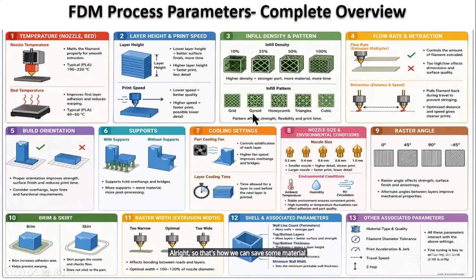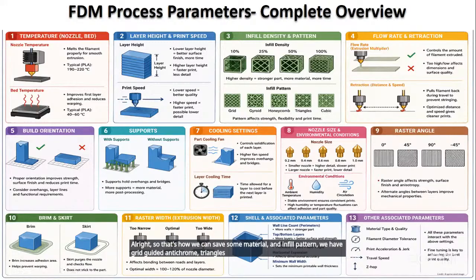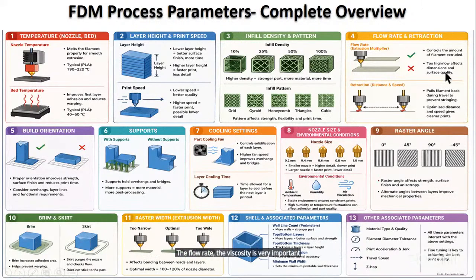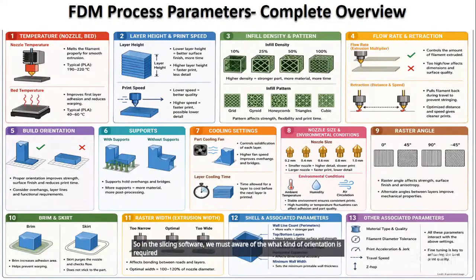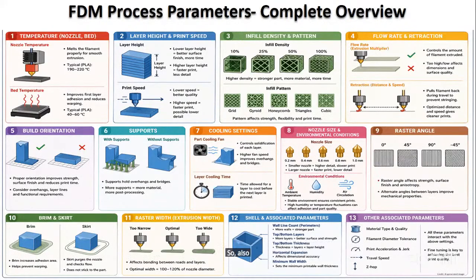And infill pattern, we have grid, gyroid, honeycomb, triangles, cubic, rectilinear, right? Plenty of infill patterns are available, and it's also influenced by biomimetics. There's a lot of work on infill patterns in the literature. The flow rate and the viscosity are very important. Then build orientation. In the slicing software, we must be aware of what kind of orientation is required, because unnecessarily you have to increase the material consumption and time. The proper orientation not only gives a good surface finish and reduces the print time, it also reduces the material consumption and time requirement, and improves the strength.